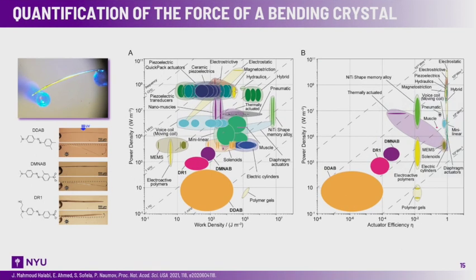So we tried to somehow quantify the force that a crystal can exert. The problem here is that if you use UV light, it interferes with the band gap of the detectors. And so in this particular case, we use micropillars made from PDMS, and we use crystals that are bent by UV light, and then we measure the deflection of the micropillar, and based on that, we can calculate the force exerted by the crystal. And then having that information at hand, we can put them on a global materials property space and see where they stand. So for example, here you can see that we have low power density, and the reason for that is because they are very small objects, but they have quite large work density, which is comparable to some other systems. And then, of course, within that group of materials, you can also see that there are better performing and worse performing materials, and that also gives us an important tool, I would say, to quantify the performance of these materials.